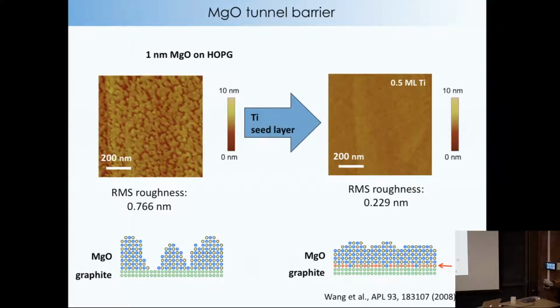Instead of just growing the MgO on top of graphite directly, we started with a titanium seed layer. In fact, it's only a half atomic layer that we put down first. And then when you grow the MgO on top, it's a lot flatter. This is just the AFM scans.